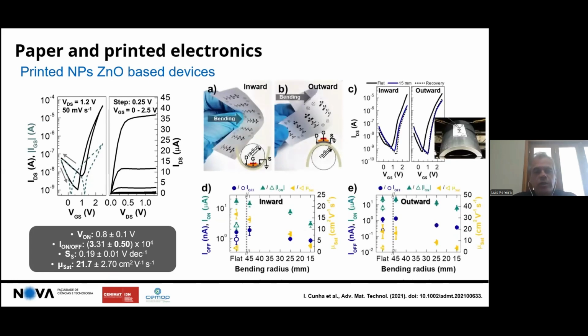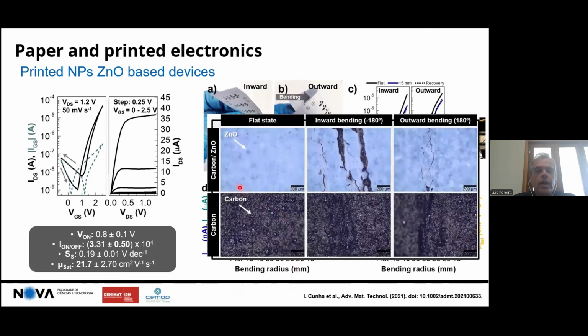Of course, as some of the previous speakers already talked about, these are intended to be flexible, and one of the drawbacks of these films made of nanoparticles is when you start to bend them. And interestingly, they behave differently if you are bending inward or outward, as you see here. And I will put here a picture just for you to understand. So what happens when it is in the flat state, when you bend inward and when you bend outward? You see that inward, it's much more dramatic for the film made of nanoparticles than the outward bending. And so this is an issue that we need to deal with.